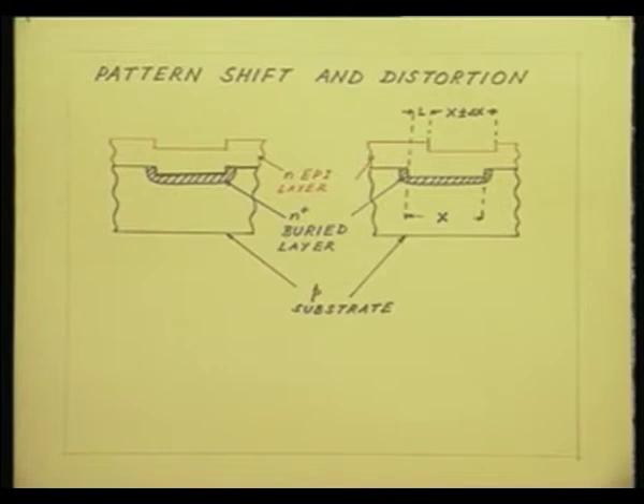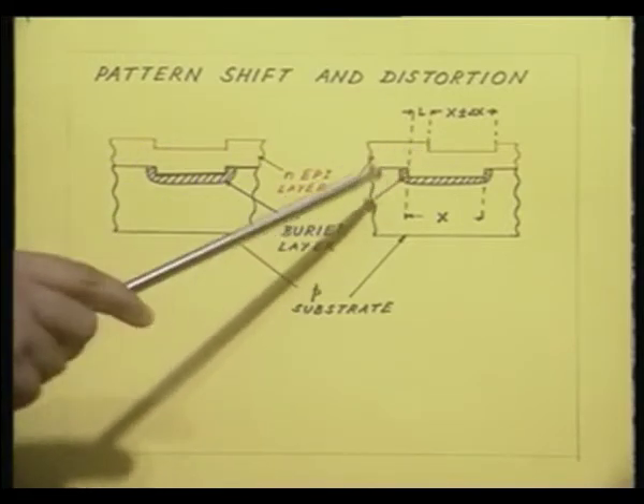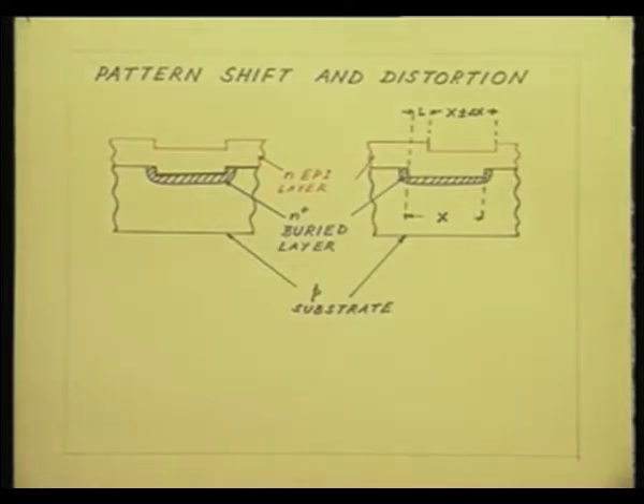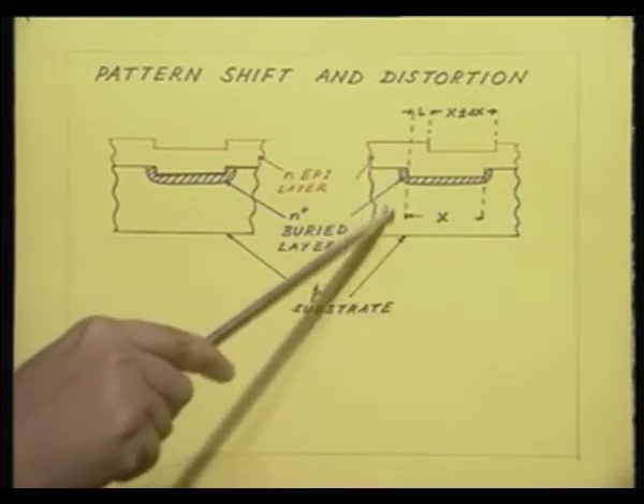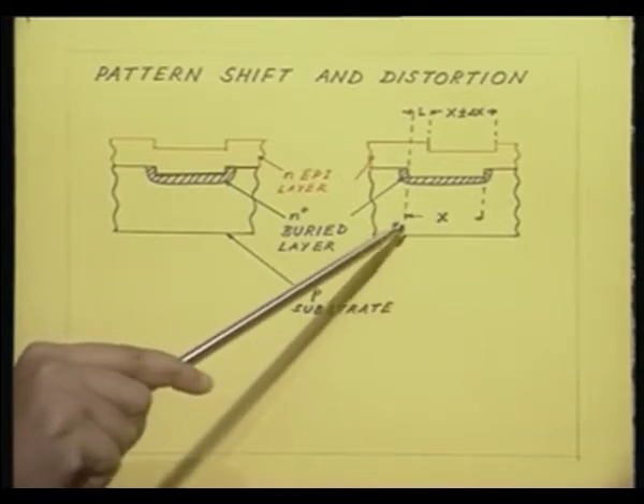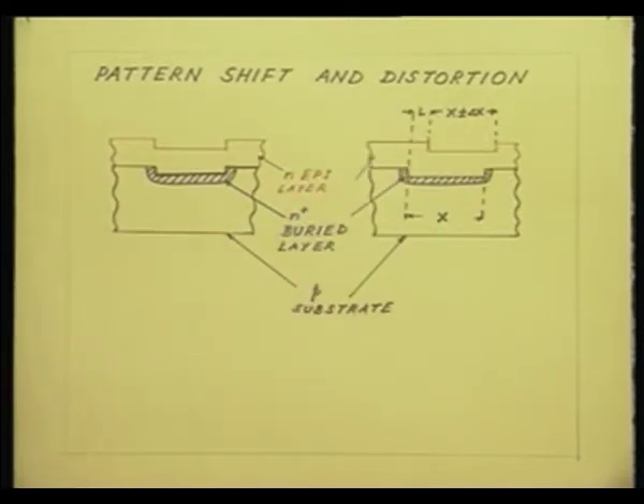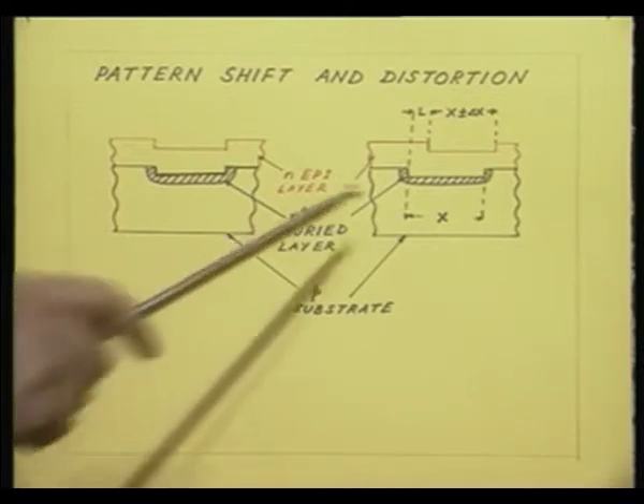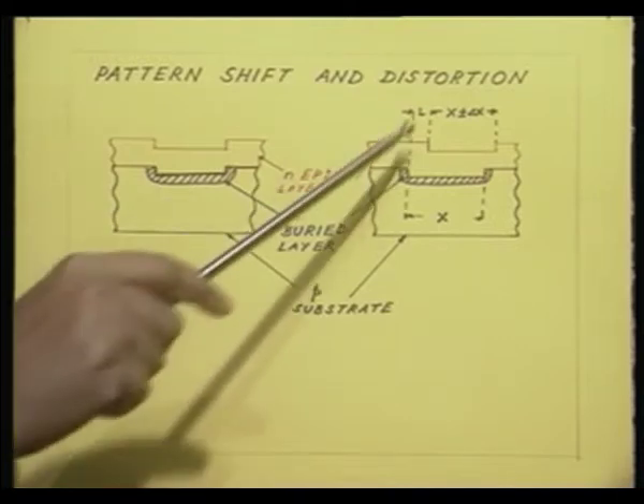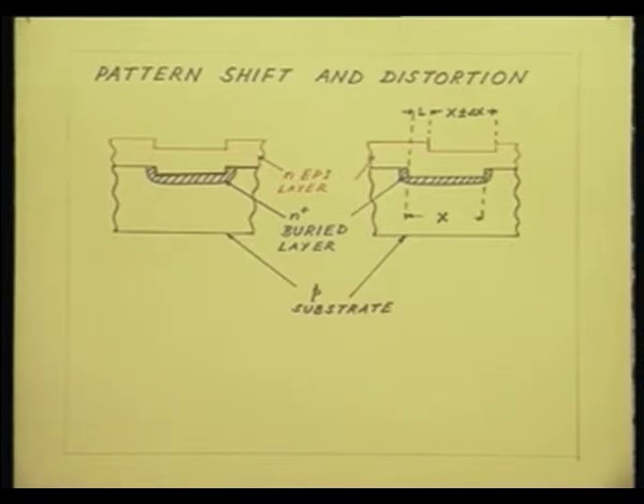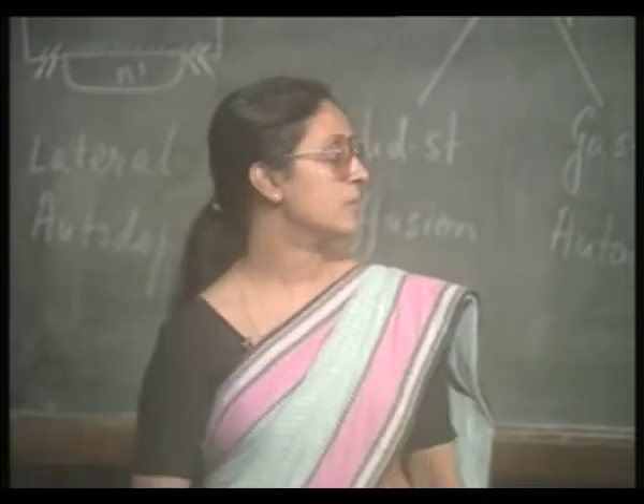So, this is what I want, but unfortunately what in most cases I am going to get is this figure. Here you see that the step is not aligned, it has got shifted. Also, the size of the buried layer mask may not be the same. Like here I have shown that this was x, the length of the buried layer diffusion, that was x, and the length of this step may be x plus or minus delta x. So, the pattern on the substrate may get shifted by an amount L, and it can also get distorted by an amount plus minus delta x. This is called pattern shift and pattern distortion.